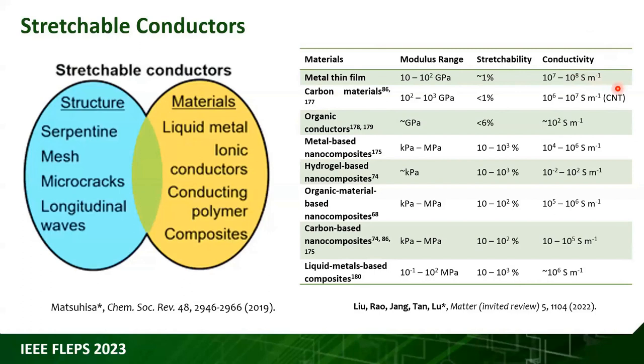But some carbon materials are approaching metal conductivity, while organic conductors are still falling behind. There's still a lot of work to be done there, a lot of opportunities as well. There are also composites and hydrogels. They are very soft and biocompatible, but not good conductivity. And liquid metal is only one order lower than solid metal. And the liquid metal is liquid, right? Intrinsically stretchable. That's why it's also very popular for e-tattoos.